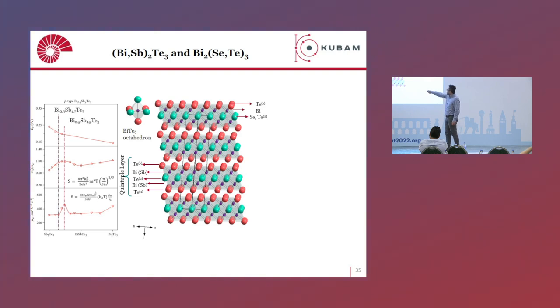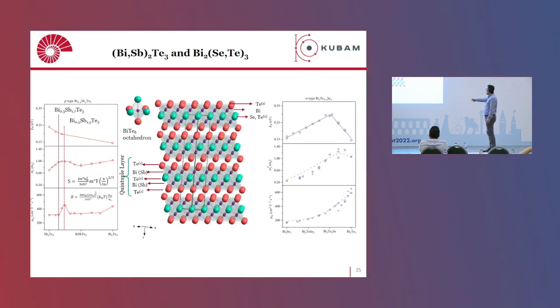One is with bismuth 0.3 and the other one is bismuth 0.5. For the selenium case, you can do the same. You can basically do a solid solution of bismuth telluride with bismuth selenide. They have the same crystal structure, which means you can combine them in any ratio you want, and you can also optimize their transport properties.